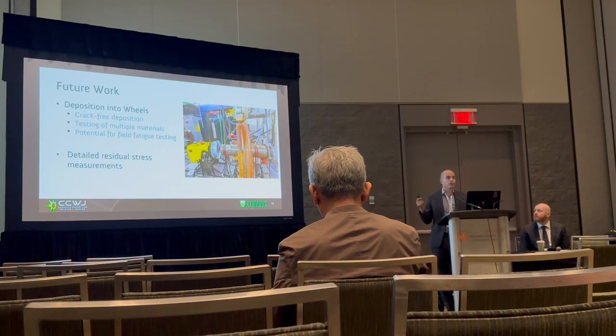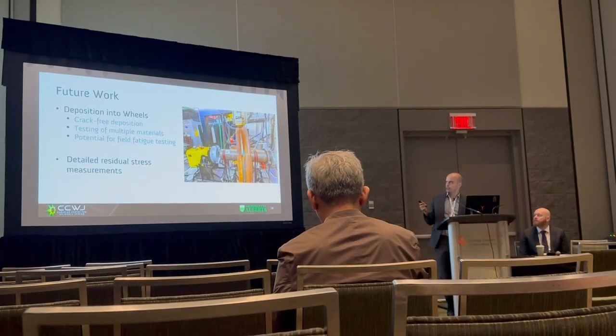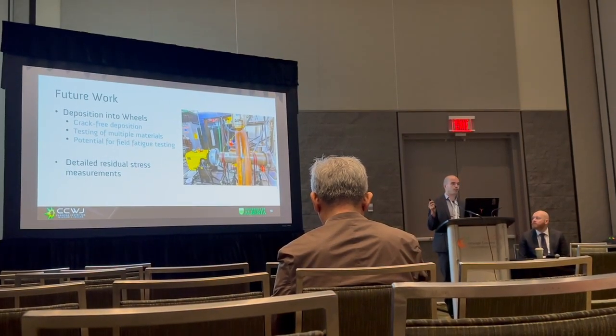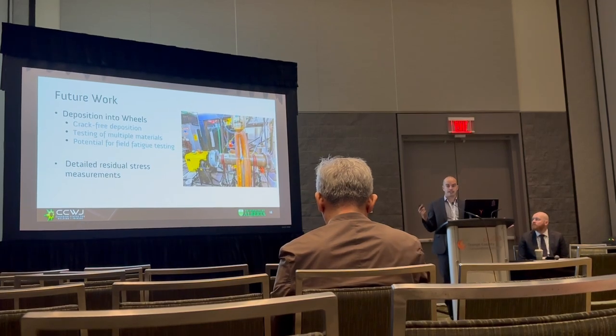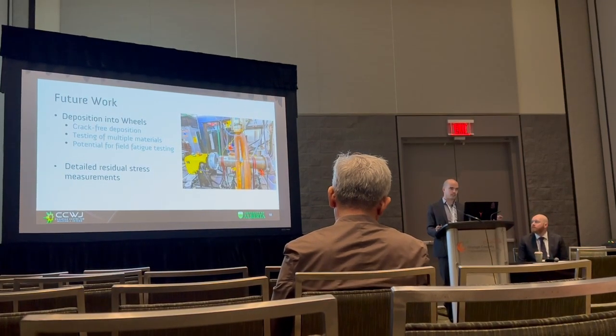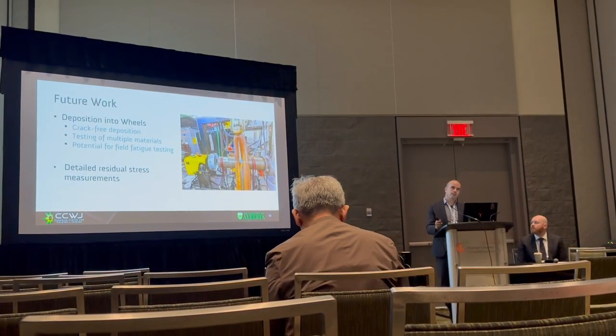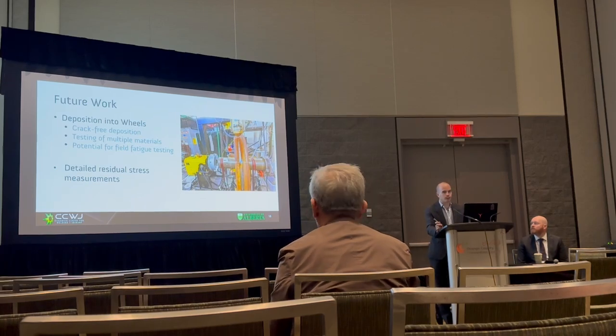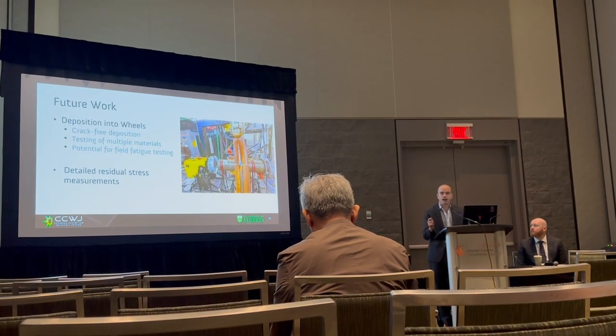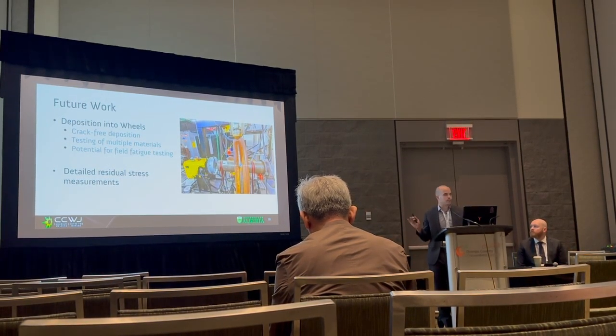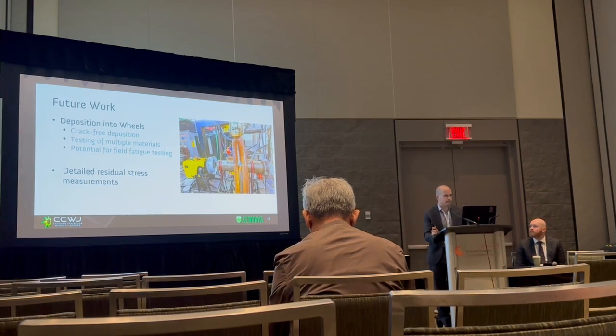They were doing submerged arc welding of wire-based consumables. I'm doing plasma transferred arc with powder-based consumables, which is allowing me to design these alloys to have these transition temperatures. They made a series of 13 welds and all of them cracked in deposition. I have managed to put a full deposition through that rim without cracking a deposit yet.